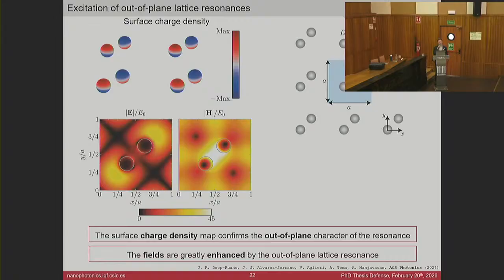I mean, at the end of the day, you will need either an in-plane electric dipole exciting an out-of-plane magnetic dipole, or the other way around, an in-plane magnetic dipole exciting an out-of-plane electric dipole. And regarding this, it's also with metallic nanostructures, but we also studied the possibility of exciting an out-of-plane magnetic dipole, and this is possible even with the metallic nanostructures. But of course, it's not a large magnetic dipole because of the small magnetic polarizability of the metal.